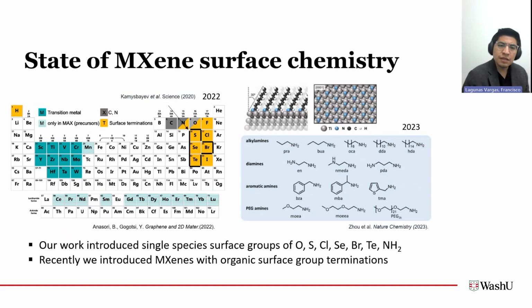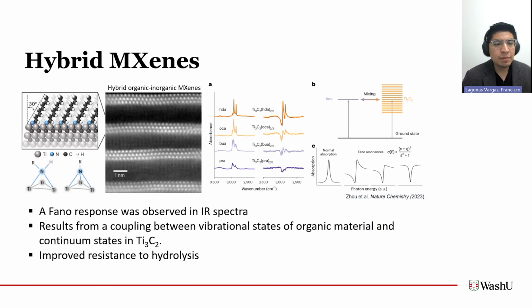Some more recent work that we've been doing is not just introducing single types of elements on the surface, but instead introducing organic surface groups into the surfaces of these h-MXenes. And that's really exciting because organic material has a really large design space with just using a few building blocks. So for example, just using nitrogen, carbon, hydrogen, and oxygen, we were able to introduce all of these different types of organic surface groups, such as alkylamines, diamines, aromatic amines, and so on. So these hybrid h-MXenes themselves were pretty interesting.